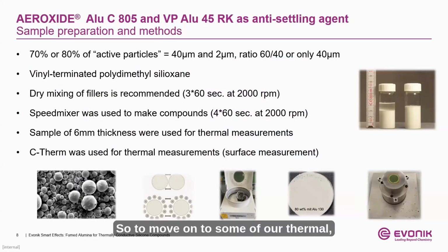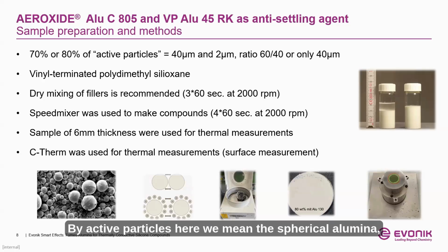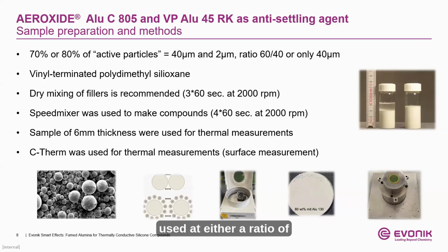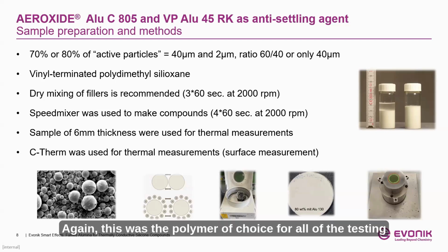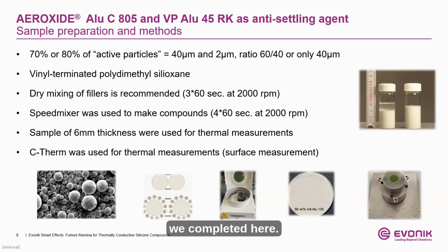So to move on to some of our anti-settling materials and our thermally conductive testing that we prepared for you here today. To outline some of those methods, some of the materials you will see will be either 70% of the active particles or 80% of the active particles. By active particles here, we mean the spherical alumina. Both a 40 micron and 2 micron spherical alumina were employed in these tests. Used at either a ratio of 60 40 in favor of the 40 micron spherical alumina, or only the 40 micron was used and not the 2 in some instances as well. This is a vinyl terminated PDMS. Again, this was the polymer of choice for all of the testing we completed here.